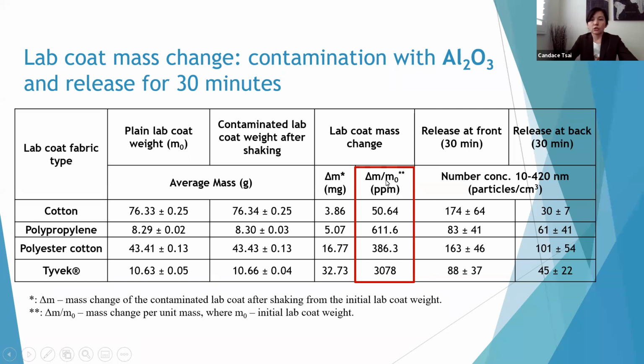Looking at this data, we found the polypropylene and the Tyvek actually get significantly much higher mass change per unit of lab coat weight compared to the cotton and polyester cotton.